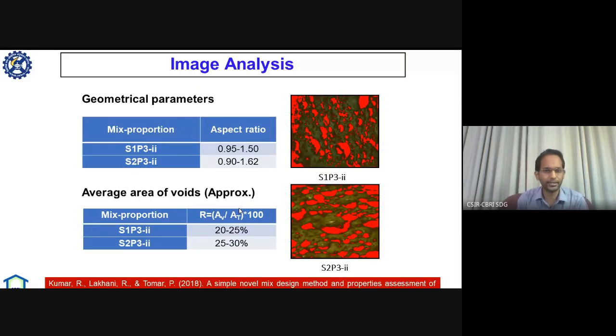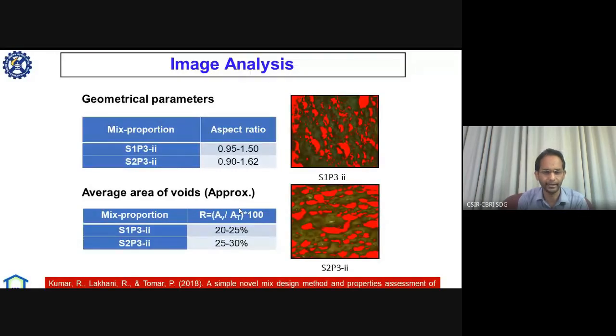We have also seen the average area of voids to compare with our theoretical entrained air voids, not entrained and entrapped air. So our main intention was to incorporate entrained air, whose size ranges from 10 micron to 1 mm, and which is not quite harmful for concrete from a durability perspective. But if you see the effect of entrapped air, the voids are quite bigger than entrained air. As you normally do the casting of normal concrete, many times there is formation of entrapped air, and the size ranges from 1 mm to 4 or 5 mm, and they are quite harmful. Therefore we limit the quantity of entrapped air up to 4 to 5%.